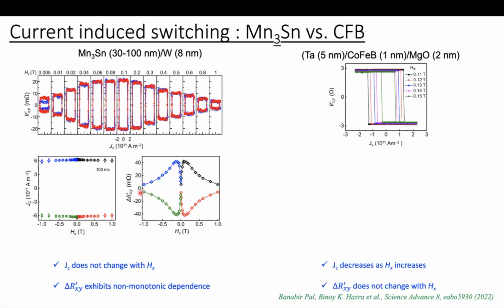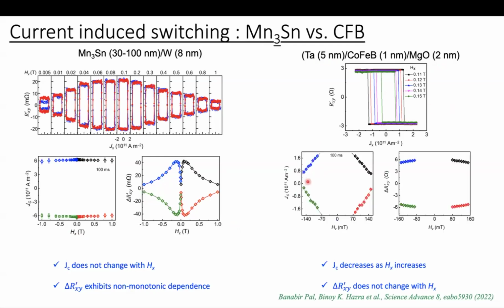So let's compare this profile with the standard ferromagnet, where spin orbit torque induced switching has been observed in various studies. We have taken a tantalum CoFeB MgO structure, and we performed the current induced switching, and extracted the current density and the switching magnitude. And what we observe, the current density, typically this is observed in various studies as well. The current density strongly depends on the bias field, whereas the switching magnitude is almost independent of the bias field.